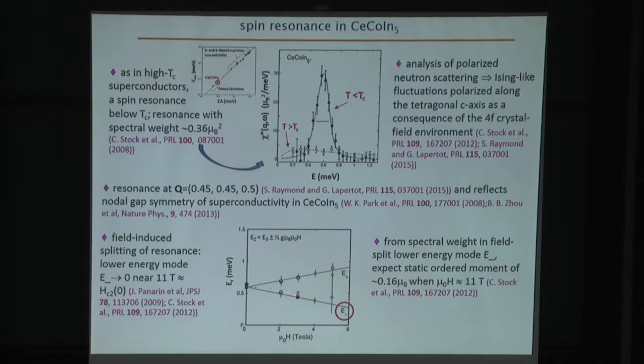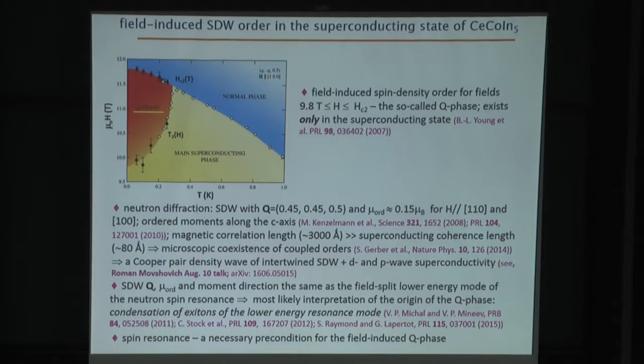So as this energy mode goes to zero energy, that means that the fluctuations in this low energy mode should become static. There should be long-range magnetic order in a field of about 11 Tesla. And from the magnetic spectral weight in this low energy mode, we would expect an ordered moment of about 0.16 Bohr magnetons, and as I said, in a field of roughly 11 Tesla.